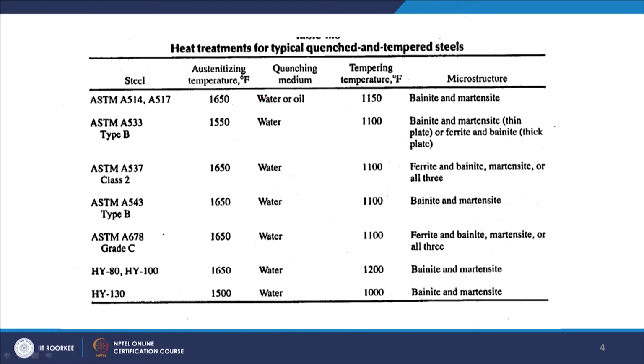But what these steels have before welding is what we can see. Say A514 and 517 steel, when subjected to austenitizing treatment at 1650 degrees Fahrenheit, followed by water quenching and then tempering at 1150 Fahrenheit, leads to the formation of bainite and martensite. Fine bainite and tempered martensite formation leads to the yield strength of 100 KSI. On the other hand, the A533 steel will have bainite and martensite with thin plates and some amount of ferrite, and bainite is also formed.